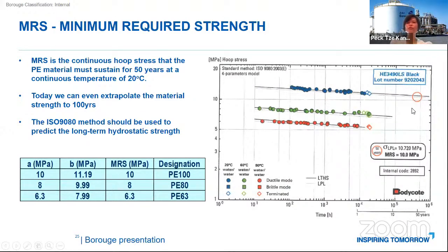So this hoop stress level will fall between 2 levels, A and B. A PE100 material simply means that it's between 10 and 11.19 MPa. Anything above it would be something like a PE125, which currently there is none in the market. A PE80 material will be slightly lower, between 8 and 9.99, and so forth. So today in the market, we are basically looking at PE100 material with very straight curves. We don't expect the curves at 80 degrees C to have a knee point going down like this, which signifies that the material is quite brittle and doesn't have enough strength.